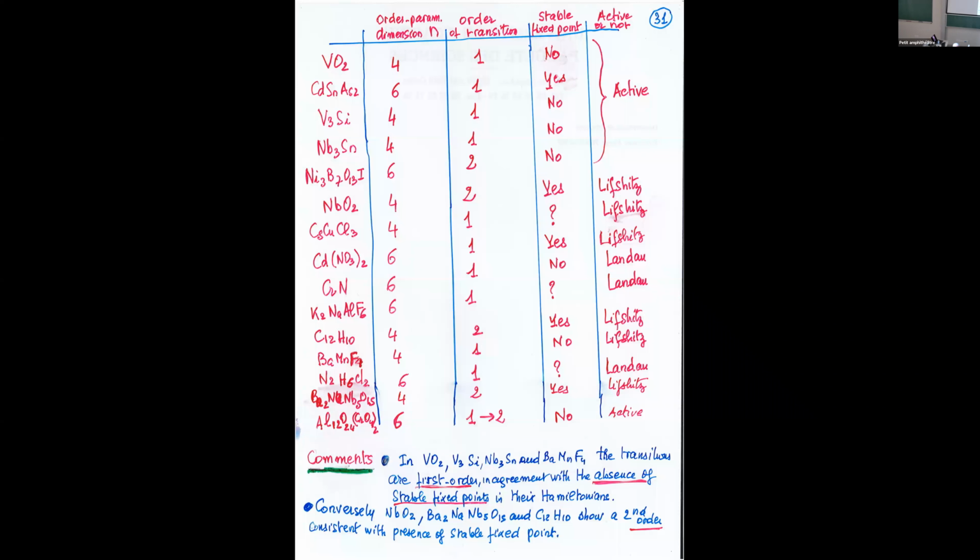Okay, what I can say only now is that you have many incommensurate phases. The field of incommensurate phases developed because with X-rays, people are now much more accurate than they were before. Also, the field of quasi-crystals pushed people to find incommensurability and non-strict periodicity in many crystals. And so, to answer your question, incommensurate phases do not necessarily violate the Lifshitz condition, but the Lifshitz condition is one possible explanation. It's clear that the order parameter varies slightly because you don't have a strict commensurability. And so, yes, the Lifshitz condition is a possible